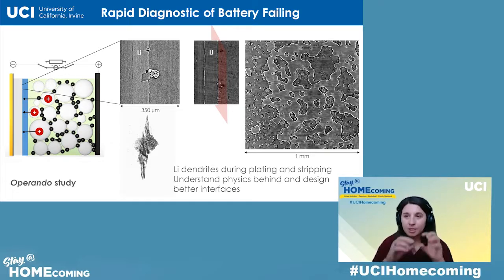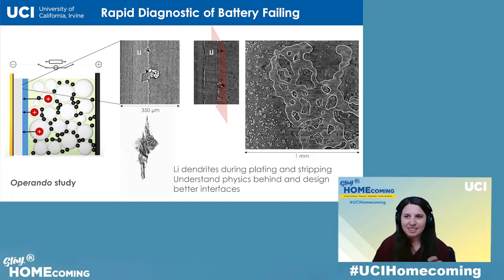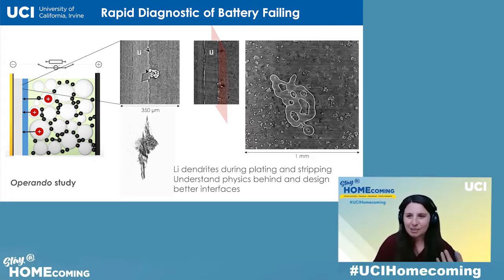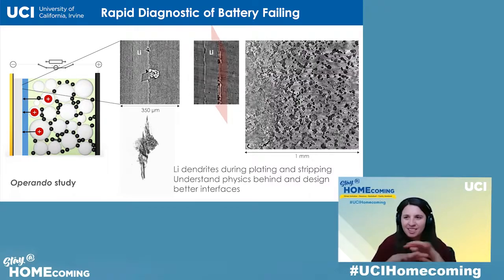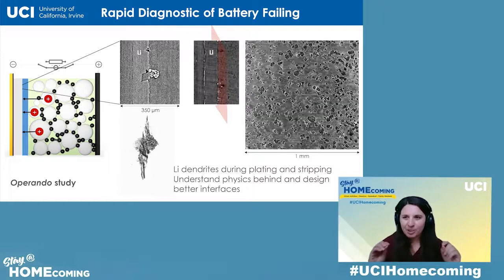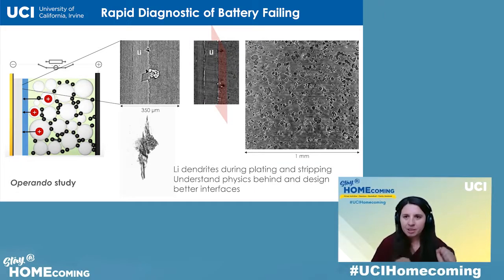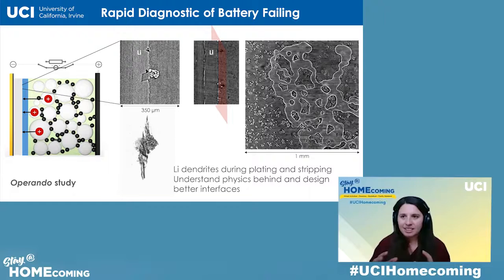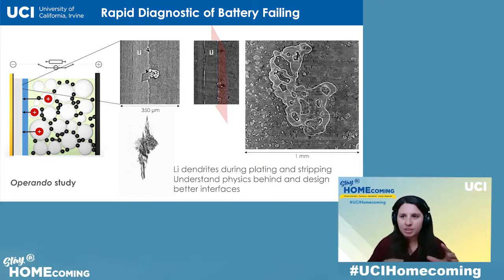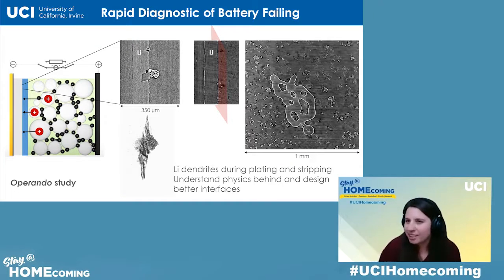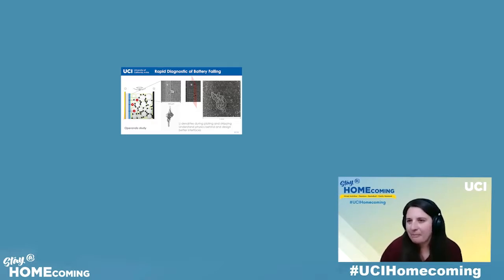First, it nucleates, it forms these little trees on the surface. Then these trees, I'll play the video again, they merge together into this very porous lithium film. And then as we move lithium back from the anode to the cathode, this lithium film kind of moves along the surface more like a liquid rather than solid, which is quite fascinating. We are the first group to show this as the battery is operating. Other groups have looked at lithium ex situ, or just looking at lithium, but not when the battery operates.